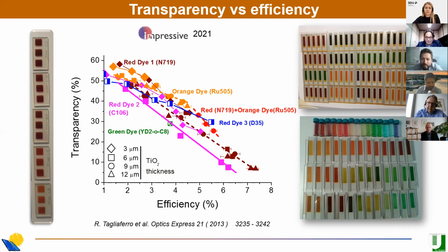This was made by the Fred Sauvage group, that they were able to get almost more than 3% efficiency with a transparency in AVT that was exceeding 75%. So this was a very big breakthrough. The molecule is a near UV dye synthesized by Claudia Barolo in Turin, and by also using a very transparent electrolyte, they were able to get this result.